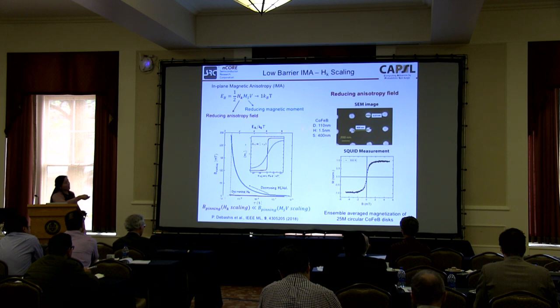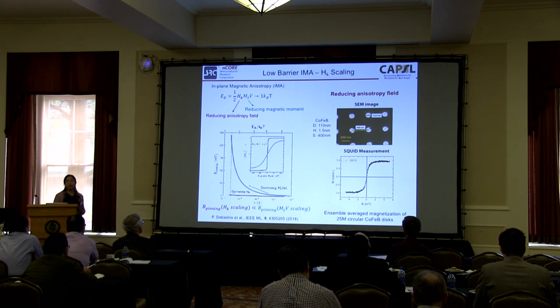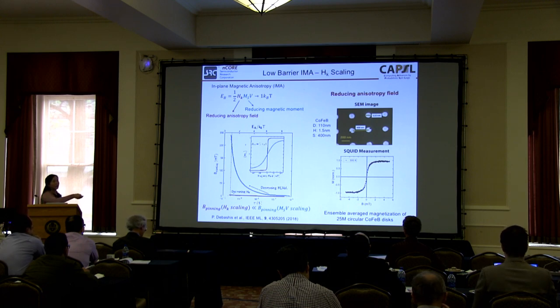And then because we don't have an electrical readout for this system, we fabricated 25 million of these circular disks and took SQUID measurements. You see the desired sigmoid curve exactly showing up. The reason is, at zero field, why do I have zero magnetization? Because these 25 million circular disks are all circling at any given moment. And because they are out of sync, the average of their magnetization together as a network is zero. Until I start to apply some input, for example a vertical magnetic field as a simple demonstration here, then you can start to guide the magnets towards one direction or the other.